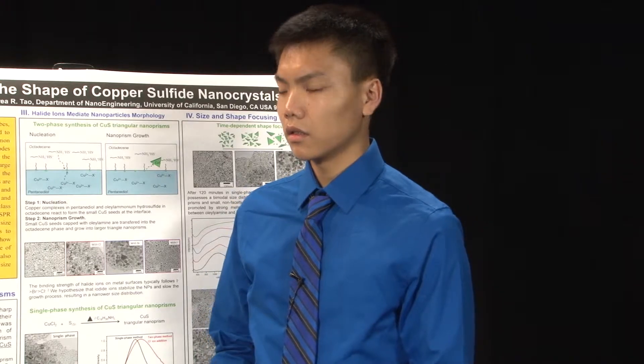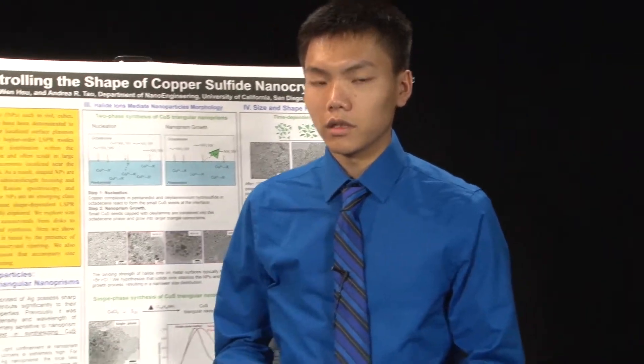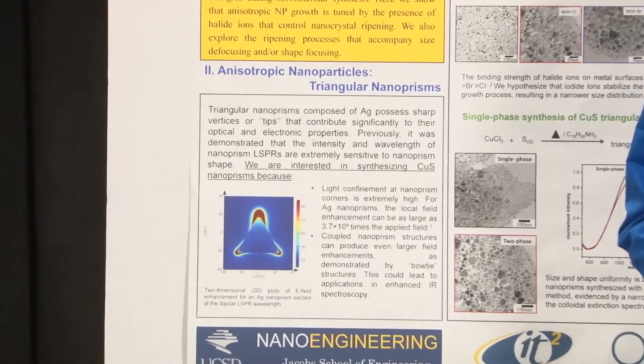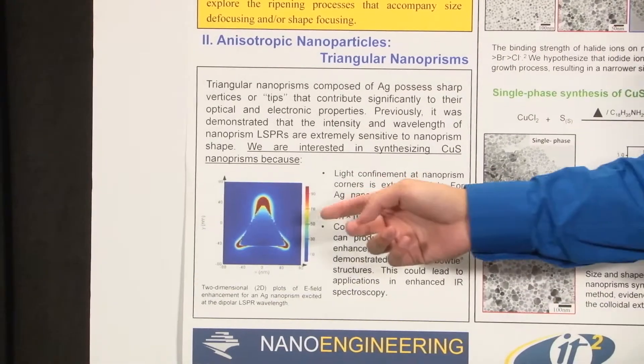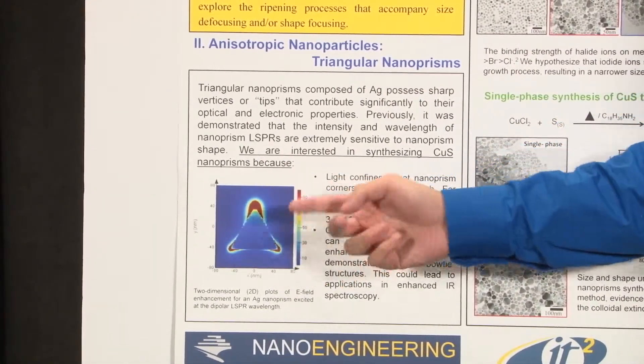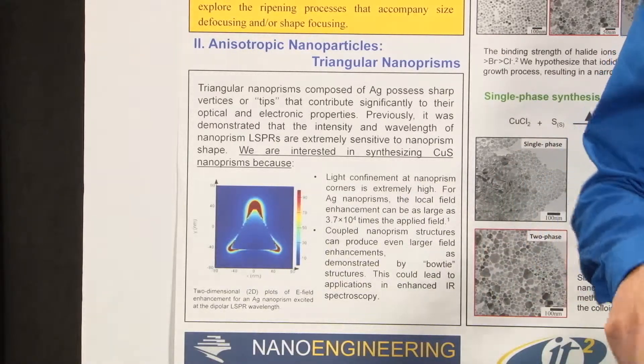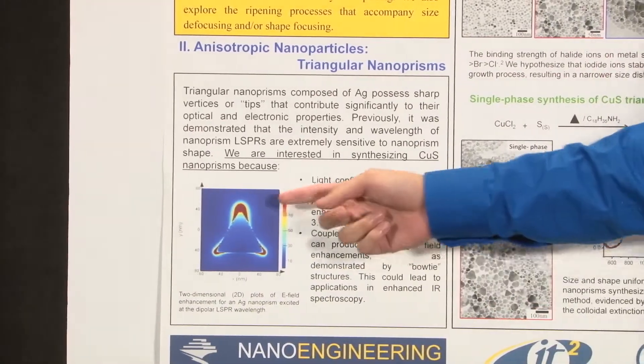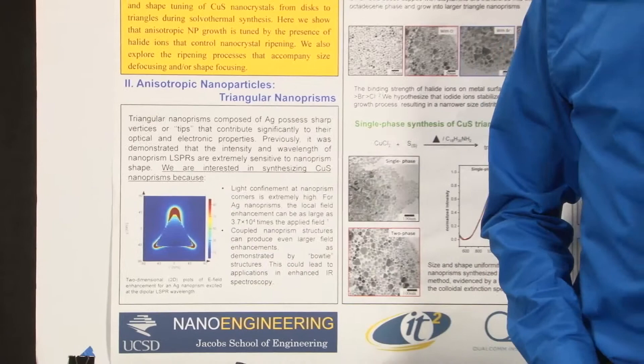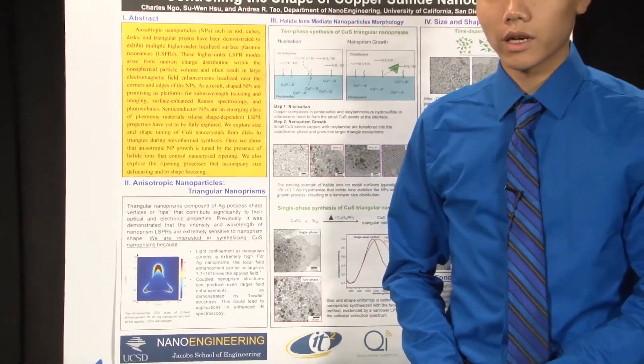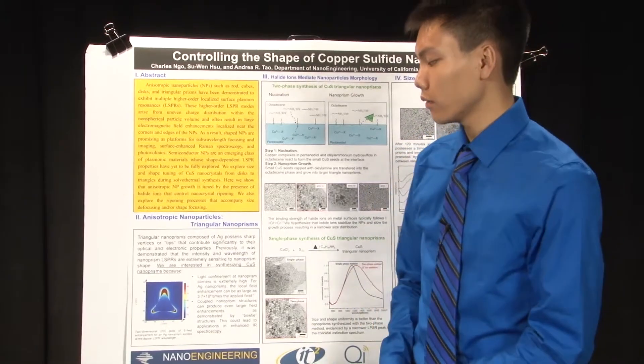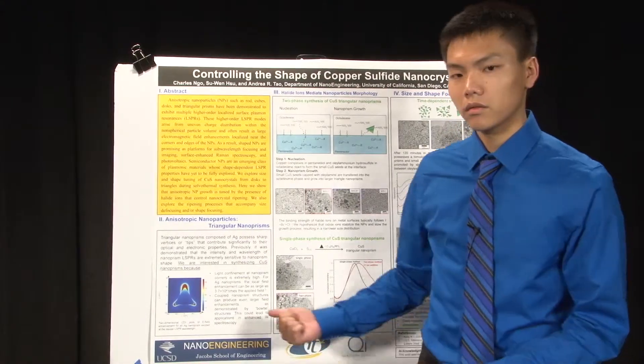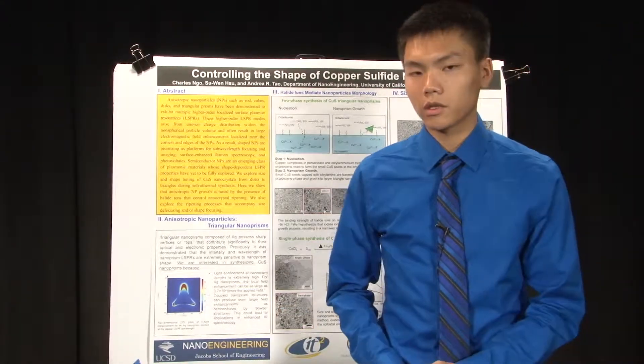Nanoprisms fit under a category of anisotropic nanoparticles because of their uneven charge distribution, meaning that for nanoprisms, most of the carrier density is at its vertices, as shown here — whereas compared to a disk, it would be a more uniform charge distribution. These higher densities of charges cause higher absorption of light based on size and shape.